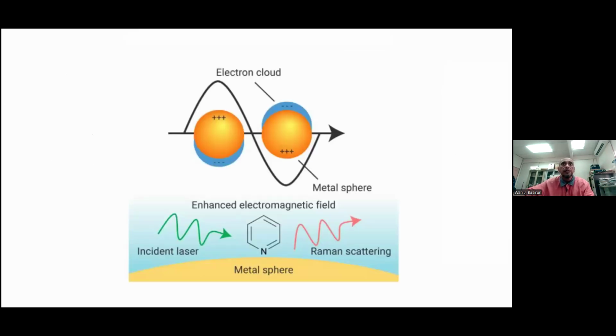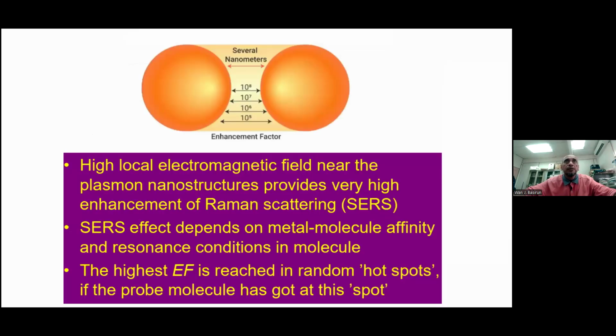So this is the case of the SERS, where you have the metal surface, you have plasmonic resonance. The top one is a plasmonic resonance, and when the laser interacts with the molecule, then you get a scattering effect. This scattering effect can be due to chemical enhancement and also electromagnetic enhancement. Yeah? So this type of enhancement, okay, this local electromagnetic field near the plasmon provides very high enhancement for the Raman scattering.